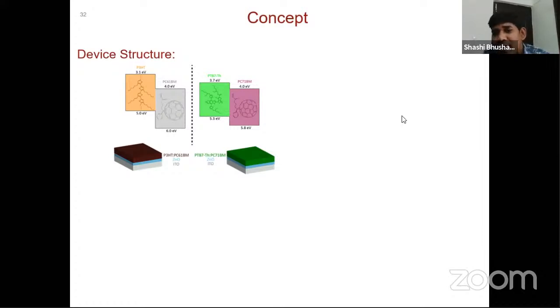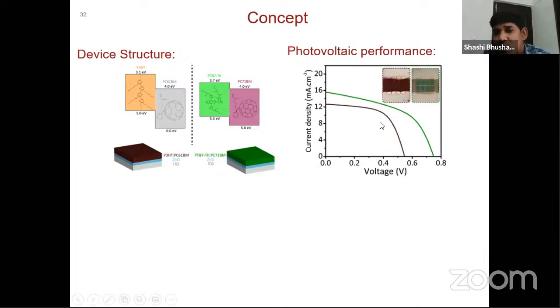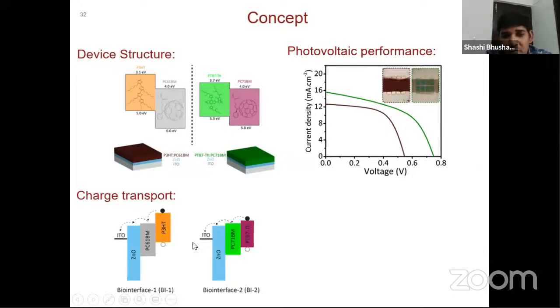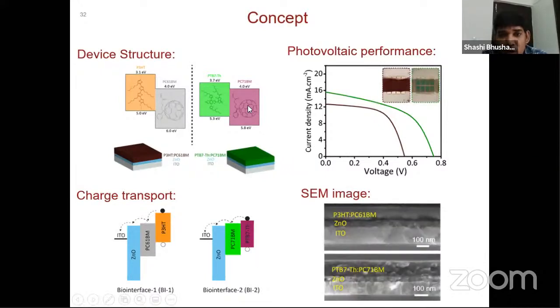So further we characterized this solar cell. Then we saw the IV performance, and you can see that there is a significant enhancement in the VOC. These are the devices in pixelated mode, there are 8 pixels, and all respond similarly. Then we looked at the charge transport behavior, and we are going to name the high open circuit voltage device BI2 and the low open circuit voltage device BI1.